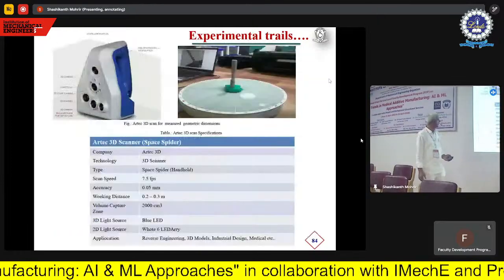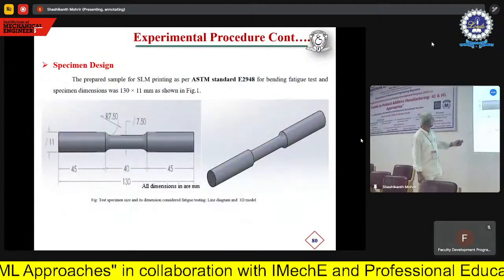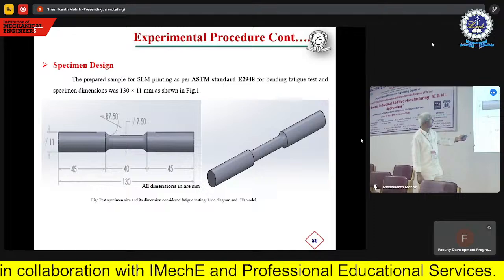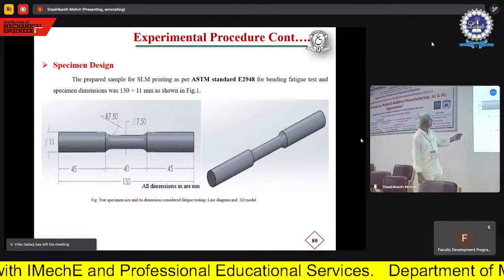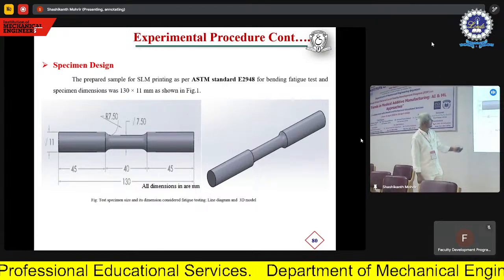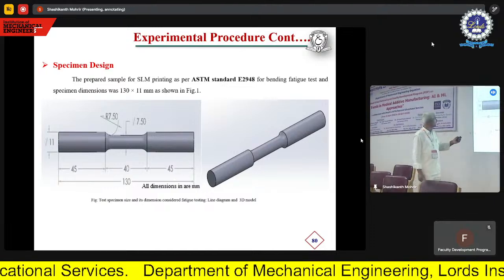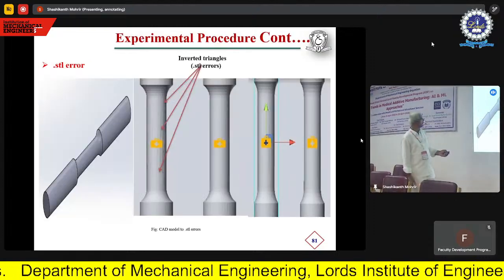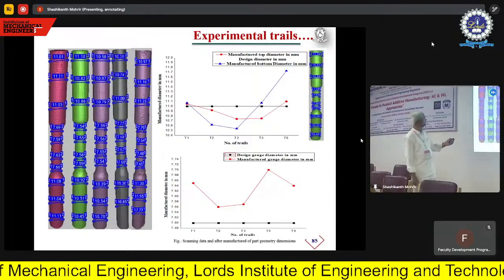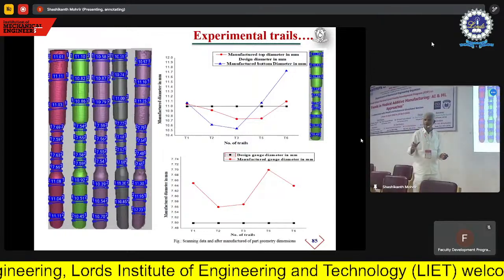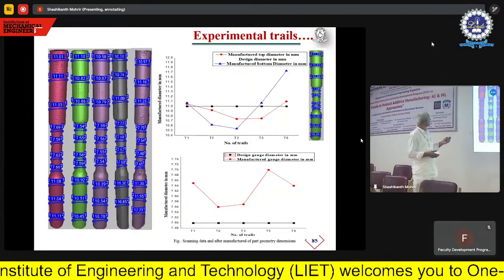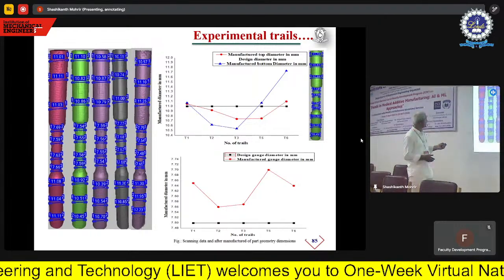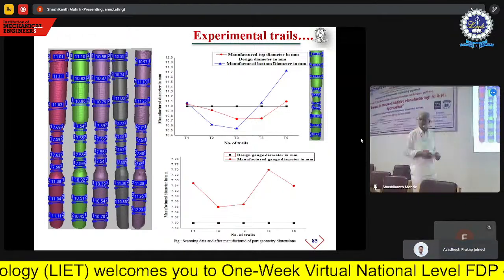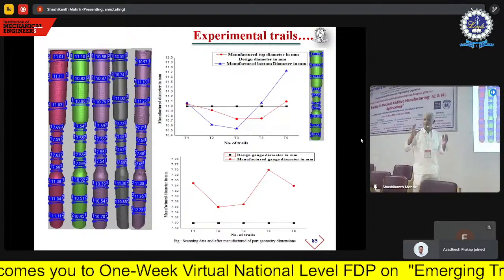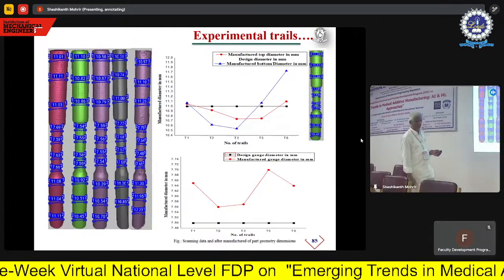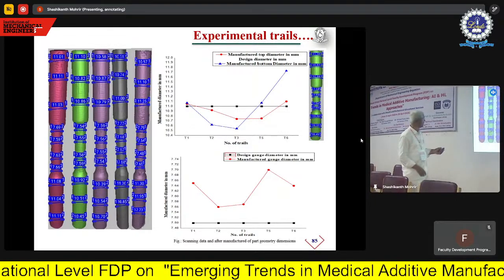So let's go back. Gauge length is 7.5, and this is 11. This is also 11, and here 7.65. So this diameter is 11, and correspondingly we should get the same in the 3D component. So distortion of 0.59 extra, 0.69 extra, 0.63, 0.66. Whatever we have in mind in our drawing, we are not able to generate or print to that accuracy.